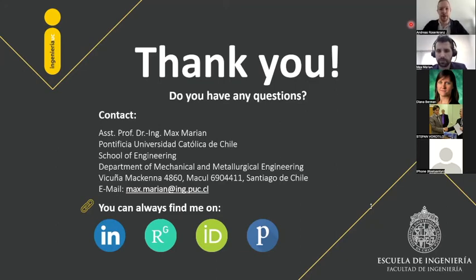Did you deposit delaminated or multi-layer MXenes? I think that's a very interesting question. And if delaminated, did you use lithium chloride or organic intercalates? Yes. The second question will be answered with the first one as well. We used multi-layer MXenes. There are some pioneering studies looking at the different tribological behavior of few layer or single layer MXenes compared to multi-layers, but I guess Andreas confirmed that actually the multi-layer ones seem to be quite beneficial in terms of tribological properties.